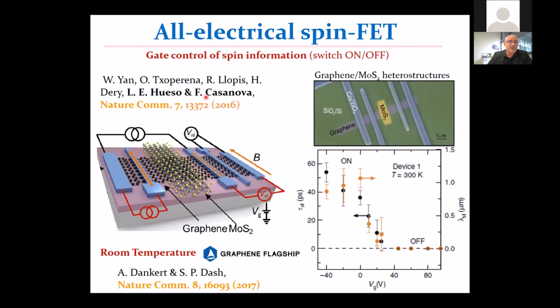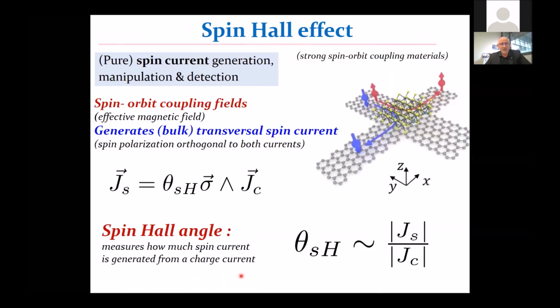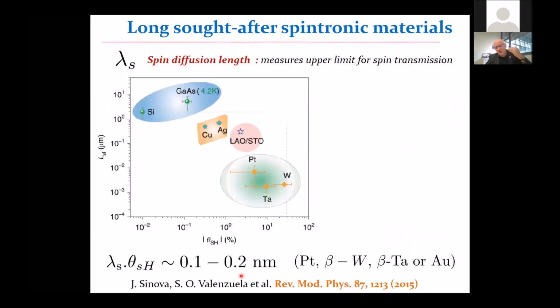This was demonstrated first by the group of Luis Hueso and Fèlix Casanova in San Sebastian, and then within our consortium we also worked on that at room temperature and showed that the effect could also be observed at room temperature. Another phenomenon that we were very interested in is the spin Hall effect, which, as I said, is the creation of a pure spin current by using the strong spin-orbit coupling. Actually, after some controversies, one of the very important aspects, beyond the spin Hall effect, is that we would like to have a material which at the same time can transfer spin information over a very long scale, but this spin information can be controlled by an electric field, for instance.